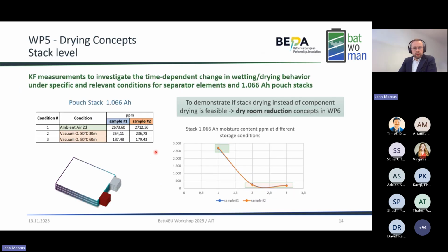Now, when we go to the stack level, which is probably more important, we actually did the pouch stack for at least 1 amp/hour here with these measurements. We also managed to get down in 30 minutes and 60 minutes vacuum drying at 80 degrees to a very good moisture level, or to an acceptable moisture level, which translated into a good performance, or at least no measurably inferior performance compared to, let's say, properly or conventionally dried electrode and cell components.